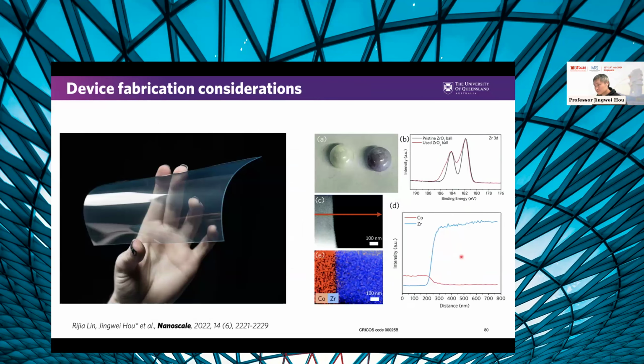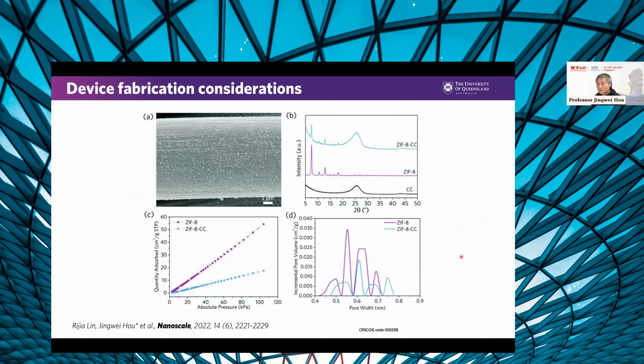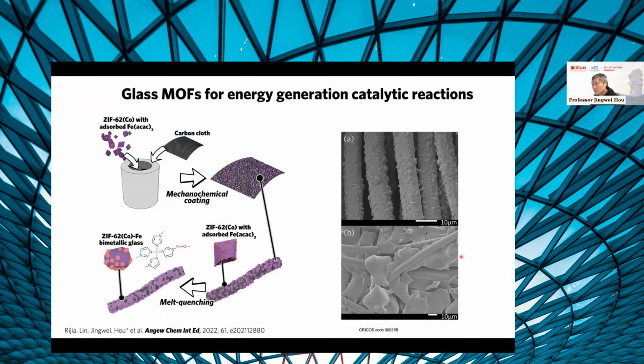And another thing is, because they are glass, they are super processable. We can make coatings, with a variety of different options by using mechanical chemistry, by using deposition, by using even dip coating, spin coating, whatever you can name it. So this is the coating pictures we made. We can coat on different types of substrate, and after coating we can simply do a thermal treatment. It can spontaneously melt on the surface of the substrate, right?